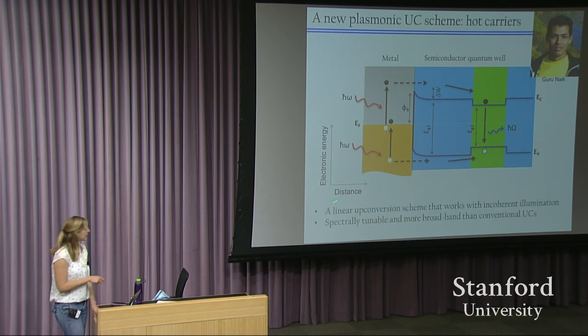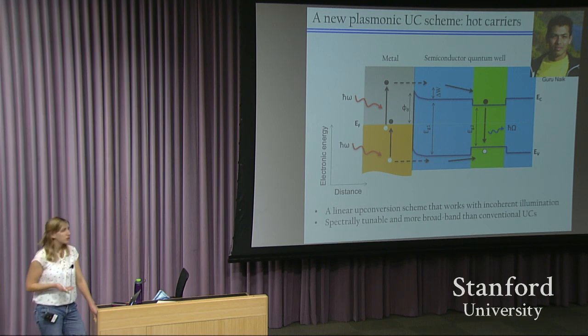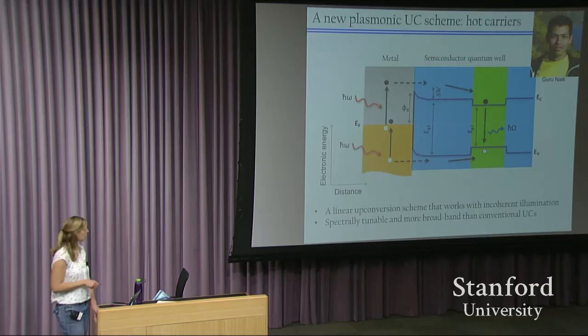So importantly, this is a linear upconversion scheme. I can talk you through in the Q&A session why it's a linear scheme. It works with incoherent illumination, so you don't need the electron and the hole to be temporally correlated to get them trapped in the semiconducting quantum well.